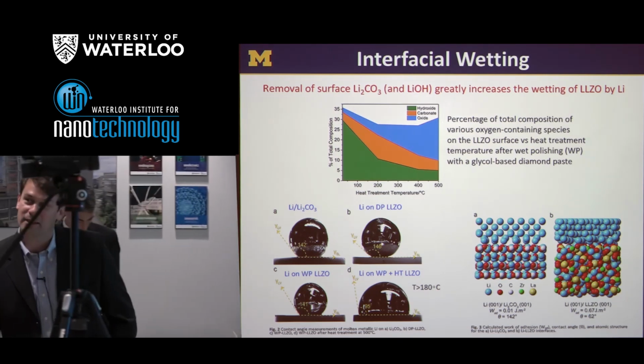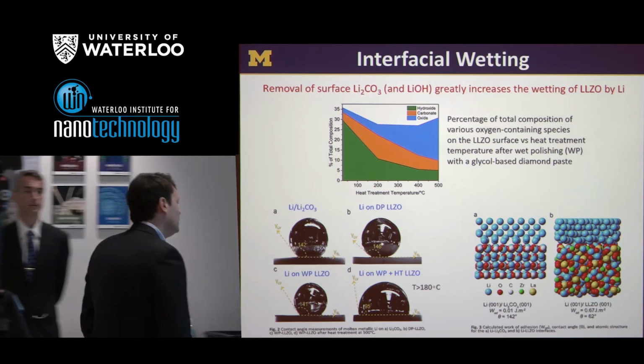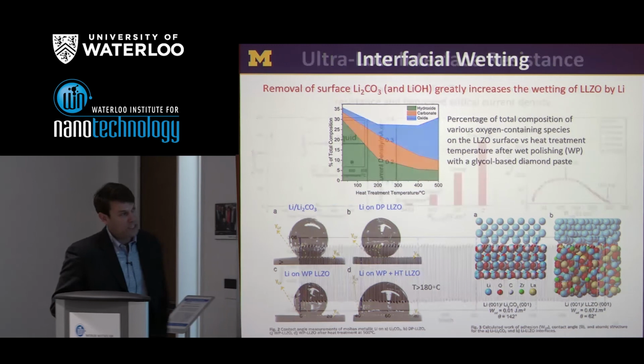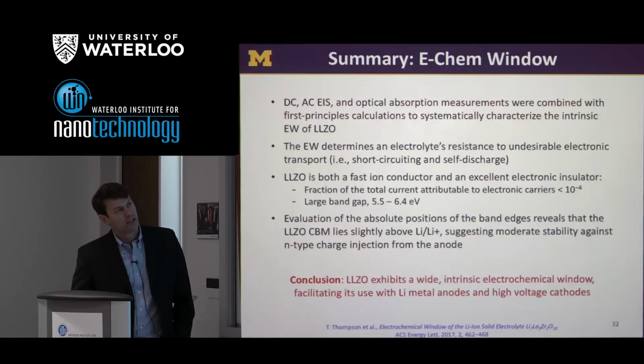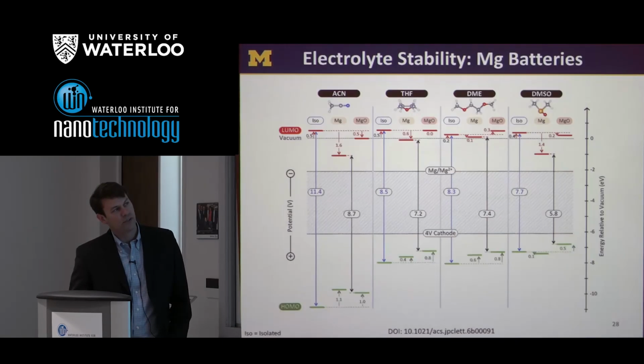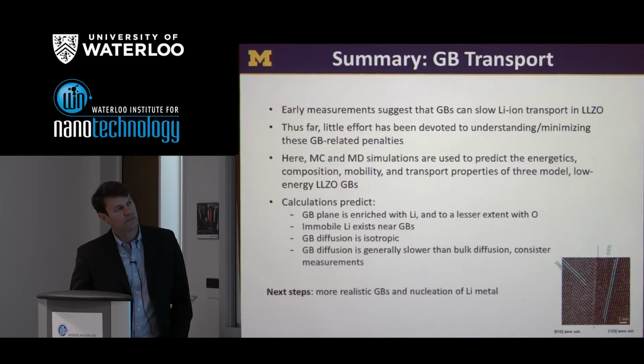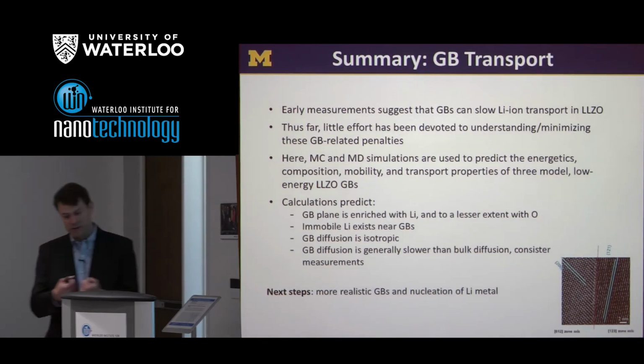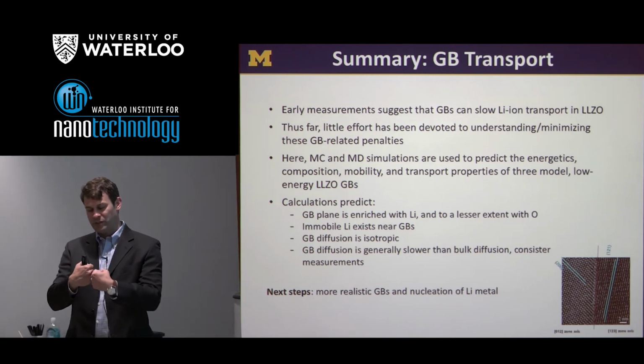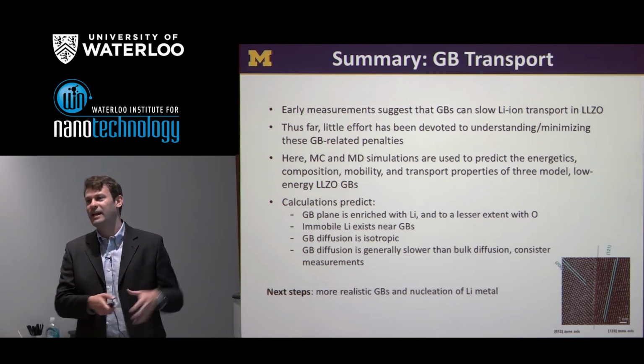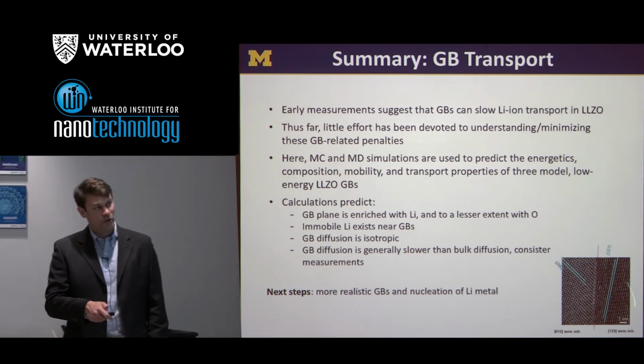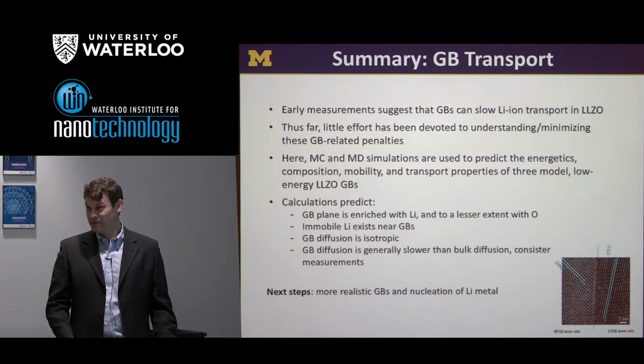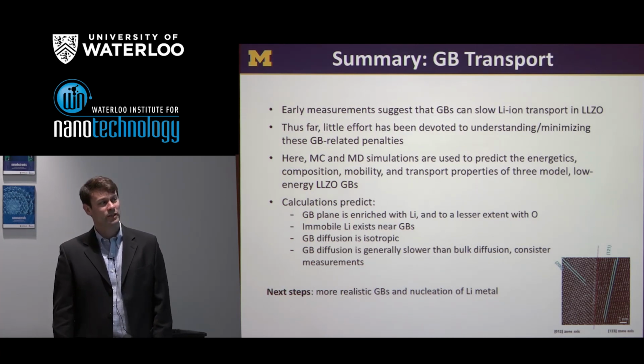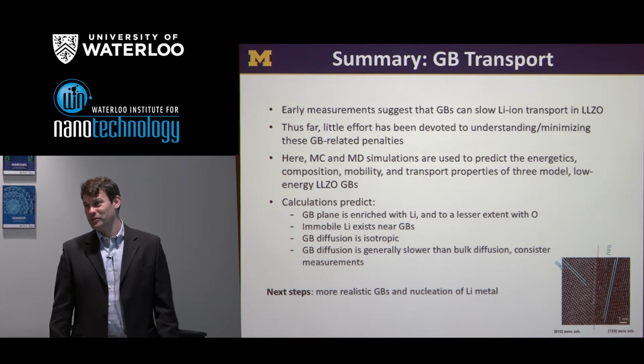Any microscopic studies on the grain boundary? Well, I have this one TEM image from Oak Ridge, which I don't think has been published. I mentioned that I would like to have some more data on grain boundaries. To specify a grain boundary, you need 5 degrees of freedom, and then in principle you also need some microscopic translations in the grain boundary plane, which we can calculate. But as far as I know, this is the only thing I'm aware of that has the atomic resolution that one could build an atomic scale model out of it. I don't even know if this has been published.